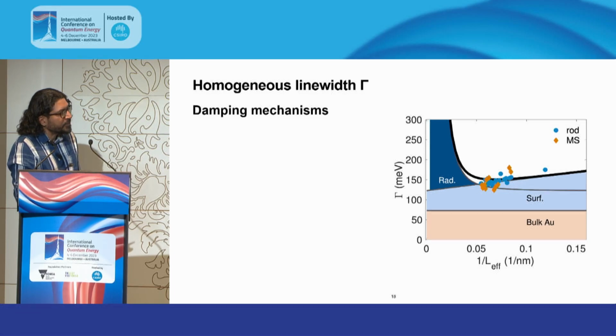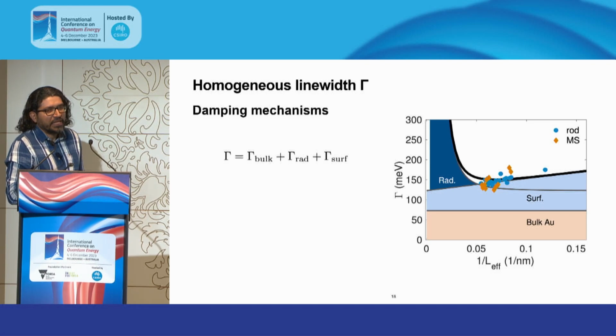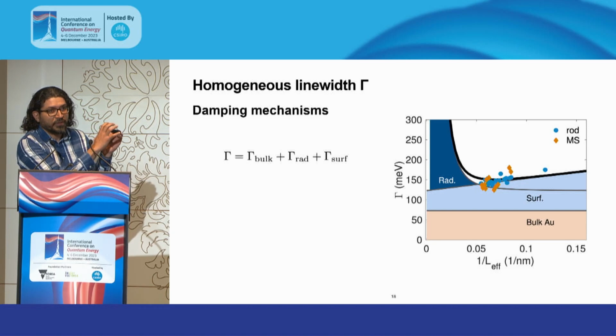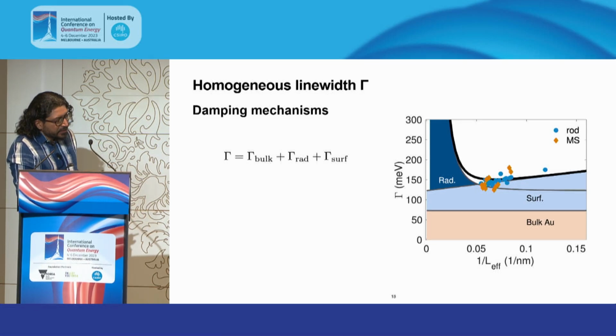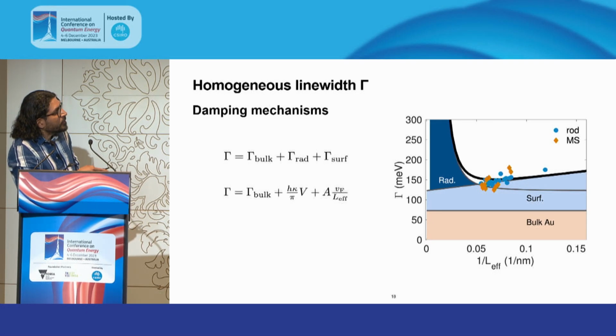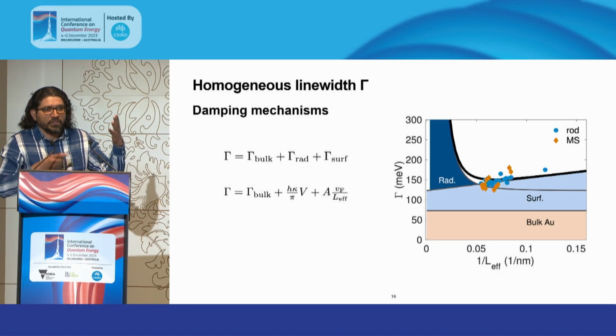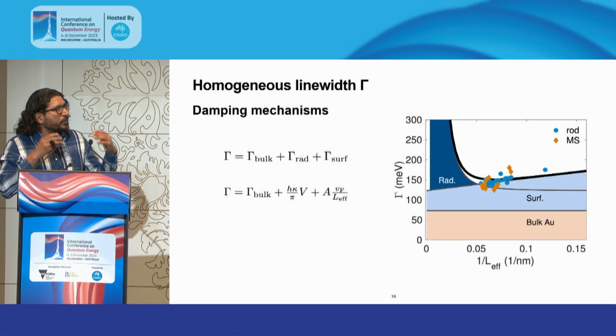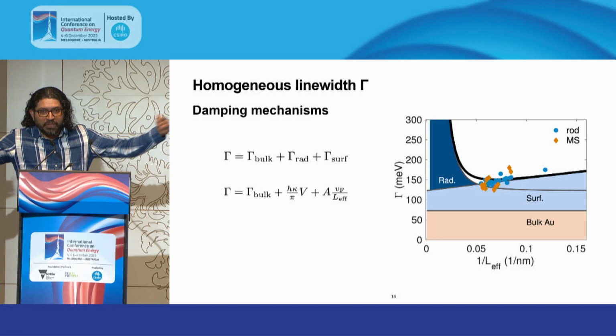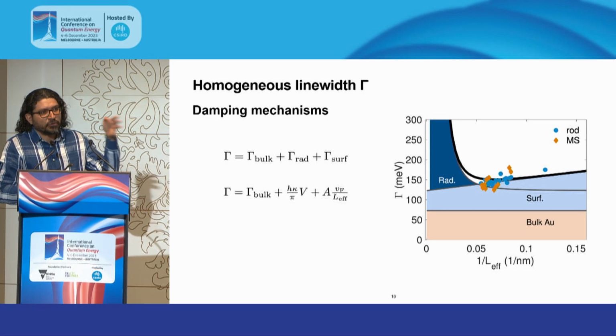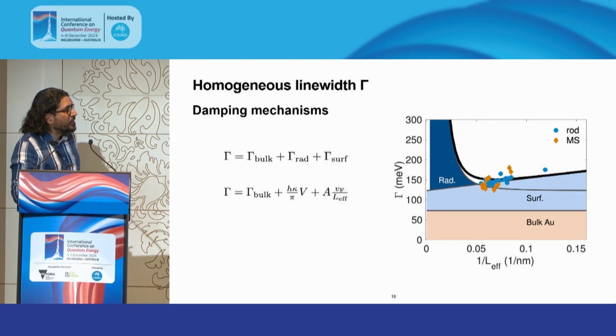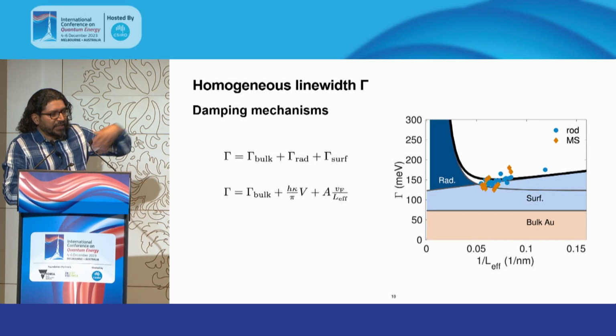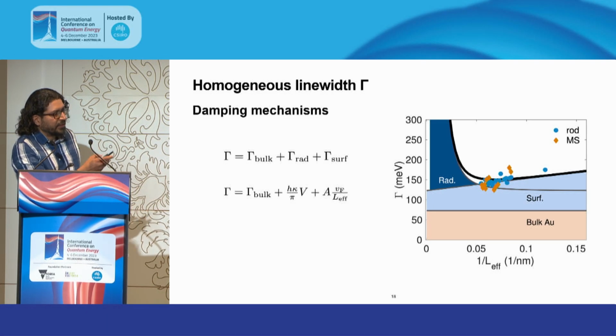And here I'm plotting the line width as a function of a parameter that is the average distance of any point along the structure to the surface of the structure. So the line width can be decomposed into contributions due to the chemical composition of the metal. For example, silver will have a very narrow line width as opposed to gold or copper. Copper will be much stronger, and this is due to electron and phonon coupling in the structure. So how easy is it for the electrons to be scattered by the nuclei?